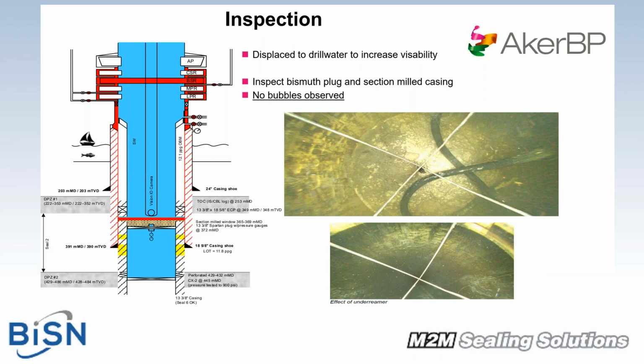So to just touch on some of the field experience that we've had, late last year, we did a job for Aker BP in the North Sea. And this was a well that they were P&Aing, and before they set our tool, they went in and perforated a shallow gas zone to actually create a leak underneath where they wanted to set our plug. They then ran in with our plug and set it, pulled it out of hole, and then one of the things they did is they ran in with a camera, and you can see the camera pictures there on the right hand side. They ran in, had a look at what the plug looked like.